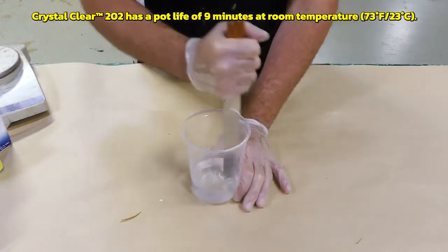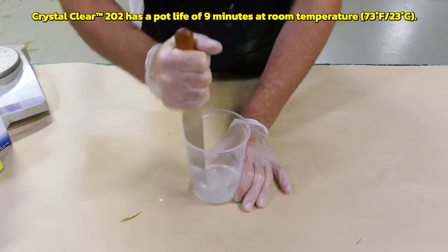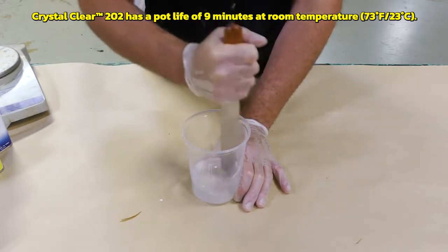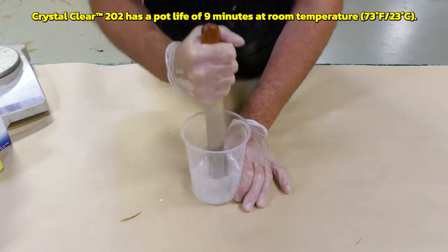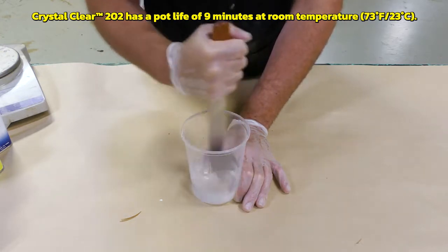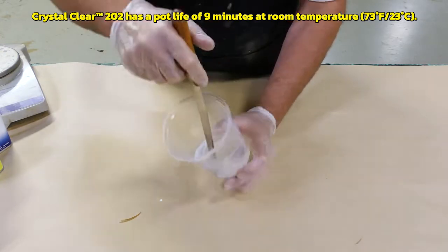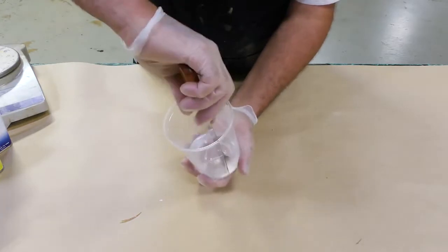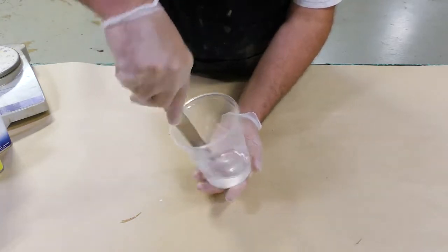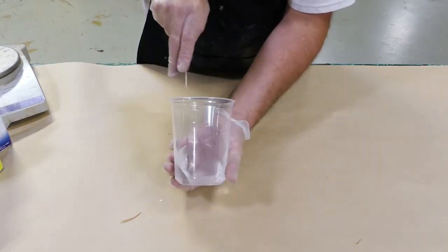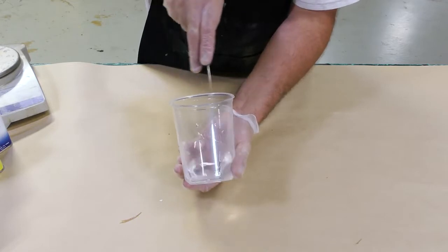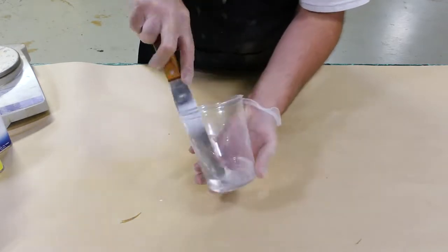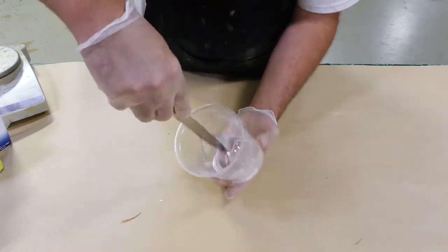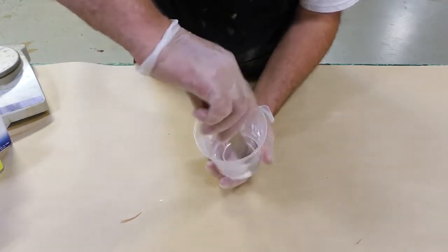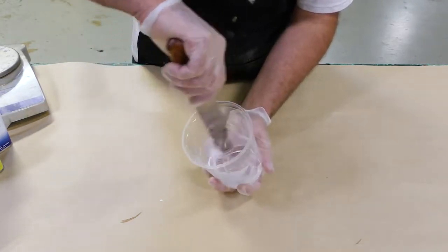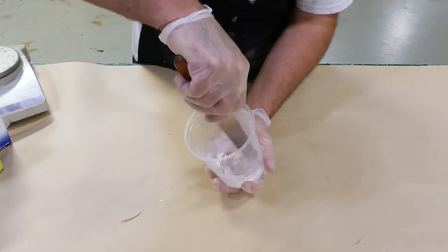9 minutes. Mix the two together, scraping the sides, scraping the bottom of the mixing container, making sure the two components are well integrated. We're going to use a metal mixing tool or a plastic mixing tool for working with the crystal clear. This will minimize the chance of moisture contamination with the material in case there is high moisture in the air and it can collect in the actual wooden mixing sticks.